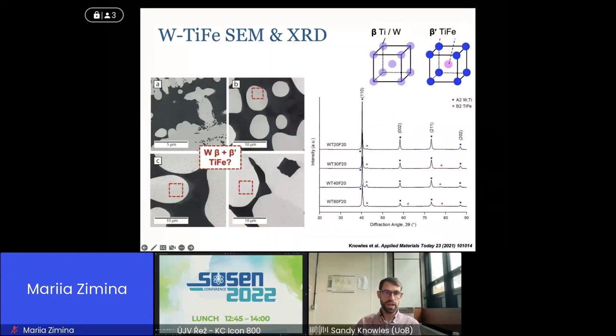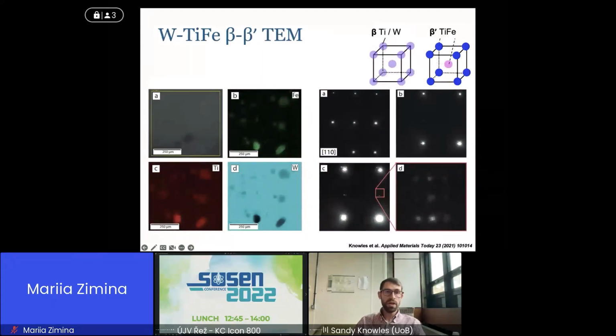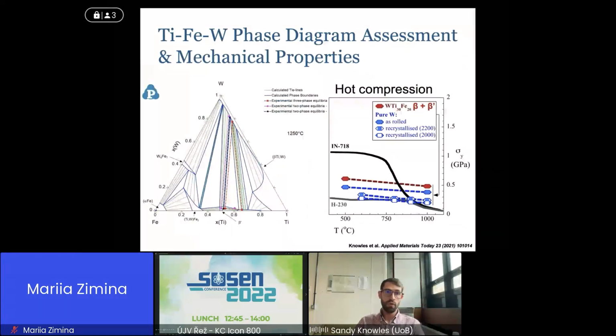So this was principally just a phase equilibrium study to understand actually what is the chemistry of the phases in the ternary system. But in having done it, we were interested within the dendrites, so the tungsten rich phase, we could see that there was a secondary feature within those dendrites. And one of the things was just porosity, but it didn't really seem to be consistent with that from the imaging. And the question was whether this is this beta prime microstructure we were really seeking. So we could zoom in and do TEM to validate both the chemistry and the crystallography, to find that we do indeed have this beta-beta prime structure. And we could start to probe into the performance of the alloy.